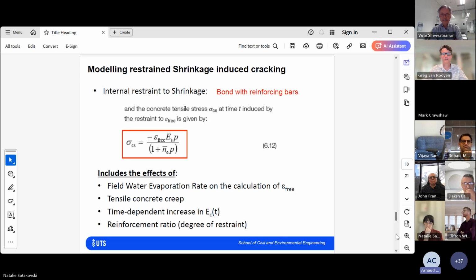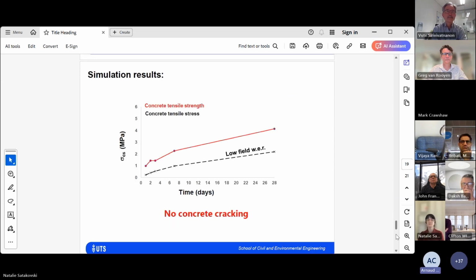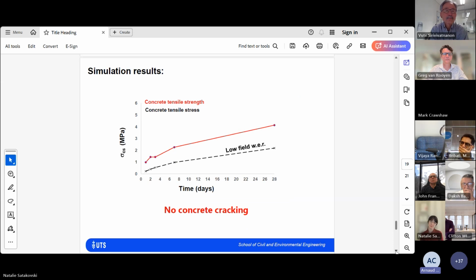If we want to be able to compare accurately the stress in the concrete to the tensile strength in the concrete. Next slide, please. So that's just some simulation results we have done using that model. The red curve is the tensile strength of the concrete. Those are experimental results, so you can see the development of the tensile strength of the concrete from day 1 to day 28. The black dotted line is the tensile stress in the concrete, which is building up due to restraint shrinkage.